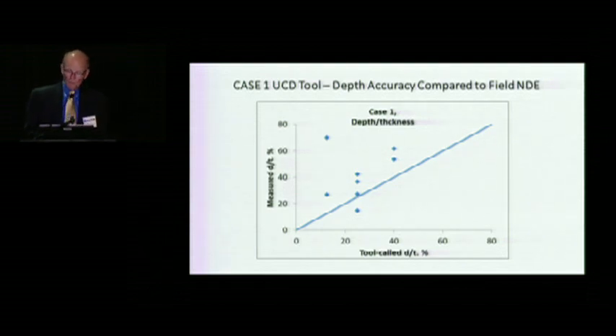Okay, so what do we find? Well, if you go through these cases, you find on the y-axis here, we have what was determined by NDE in the field versus what was called by the tool on the x-axis. And the data on the x-axis are stratified because in some types of tools, you get the data in buckets of size, and we then move it to the deepest size of that bucket. And you can see in this case, the NDE appears to say that the ILI missed some really severe defects. Well, we don't think that was true. That pipeline never had problems as far as we know about after that, so the likelihood is that the field NDE wasn't very good.